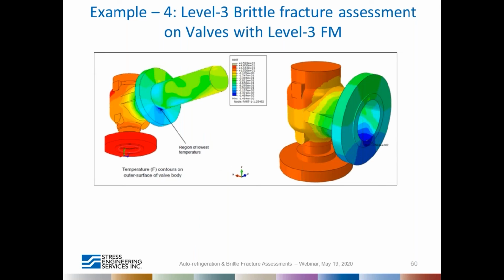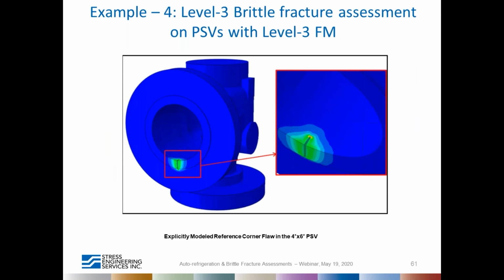For example, in this case, you can see that for this valve's flange location, the temperature was very low, being minus 147 degrees Fahrenheit. This is in methane service, and Joule-Thomson effect was the reason during the relieving, and a reference flaw approach had to be invoked, which involved a level 3 Part 9 assessment as well. So the complexities are there. However, the solutions are provided in the standards to address any kind of complexity.